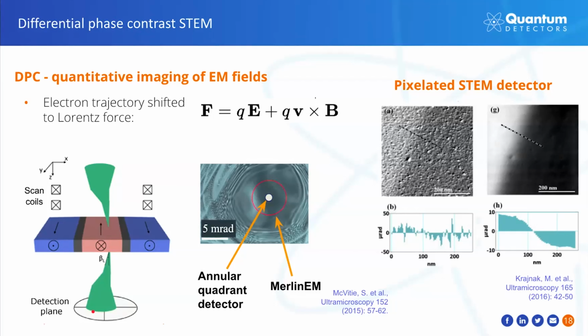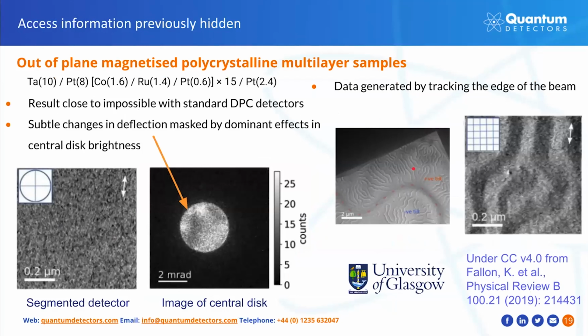In the example on the right, we can still see that the magnetic structure is faintly visible, even in the more noisy image. But in a lot of materials, we basically don't see anything. An example of this is imaging of out of plane magnetized polycrystalline samples. In this case, the situation is even worse because the material is multi-layer, with only a fraction of the thickness consisting of materials with magnetic properties. So in this more complicated formula, it is the cobalt which was out of plane magnetized.